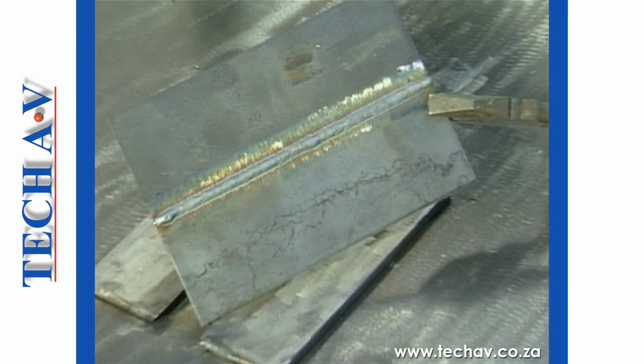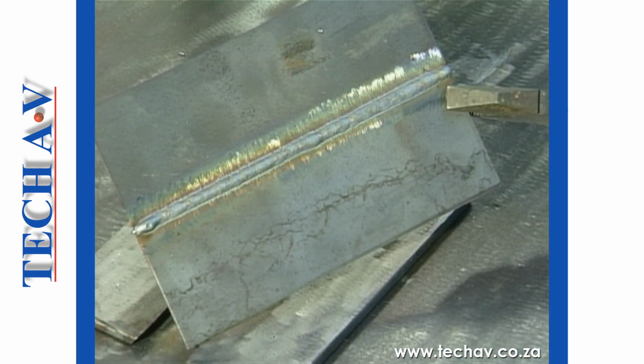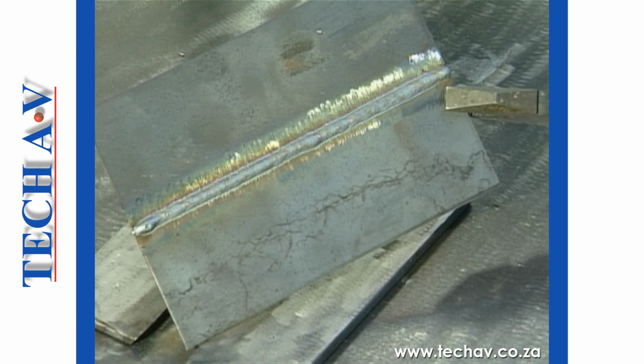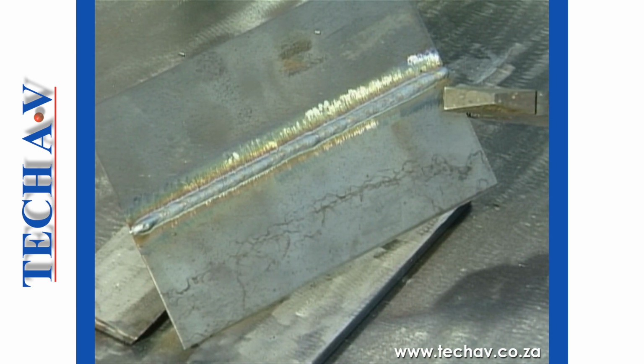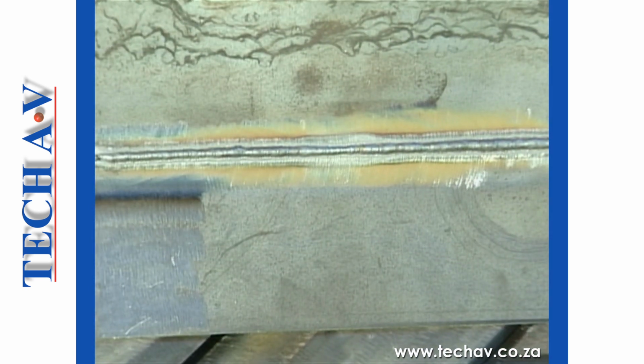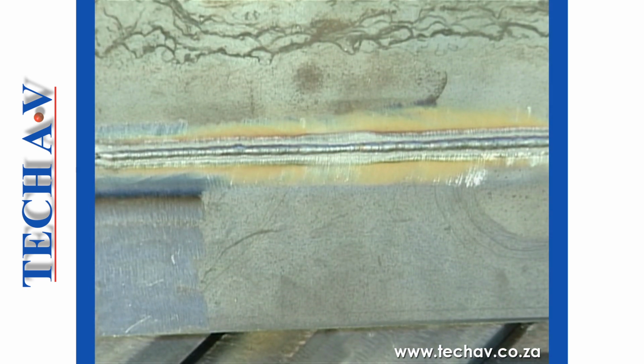Here we can see that the bead width is reasonably uniform all along the seam. There is some spatter, but this is not excessive for short-circuit transfer. On the reverse side, we see that we have full penetration of filler as indicated by the narrow root bead.